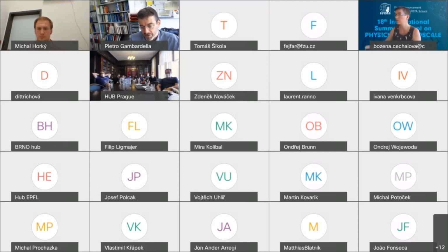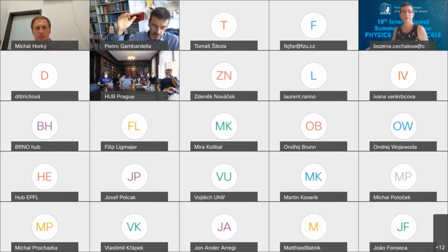The second question is, suppose you have a given spin accumulation at the interface of platinum, and then you place a ferromagnet on top of it. Then these non-equilibrium spins will diffuse into the ferromagnet and be absorbed. Okay, so this absorption depends on the thickness of the ferromagnet. If the ferromagnet is too thin, you cannot absorb all the non-equilibrium spins, and so the spin orbit torque would be smaller. There is an optimal thickness in which all the injected spins can be absorbed.